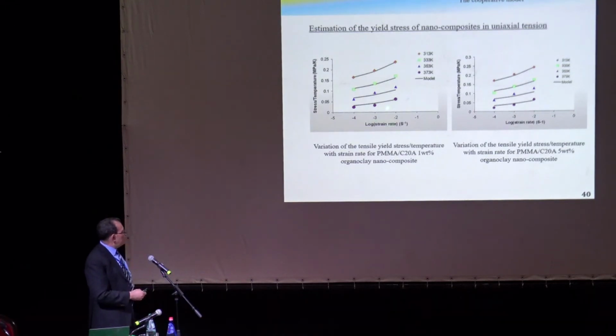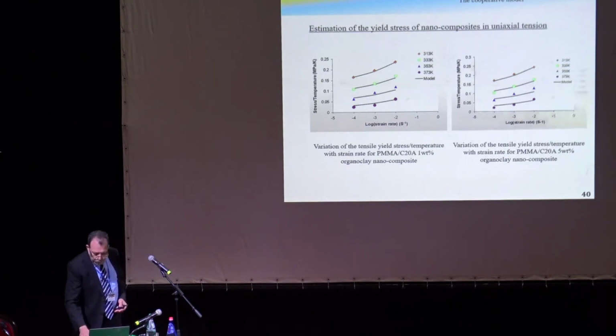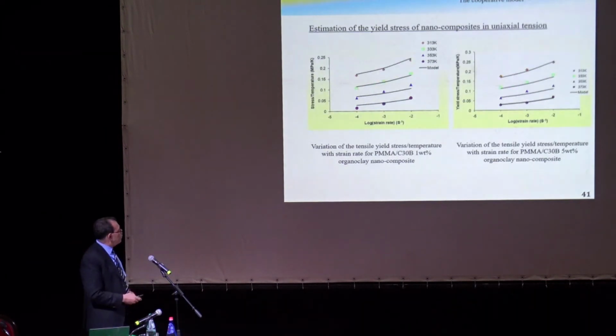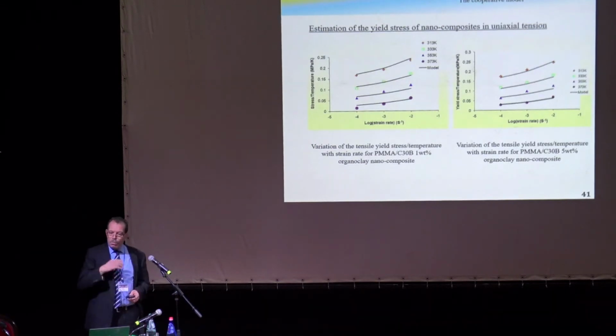Okay, for 1% of these nanoclays and for 5% of these nanoclays. The same thing for the second type of nanoclay, 1% and 5%. Also, the fit is very nice, at least within the quasi-static range. Just keep in mind that this cooperative model, we published several papers.